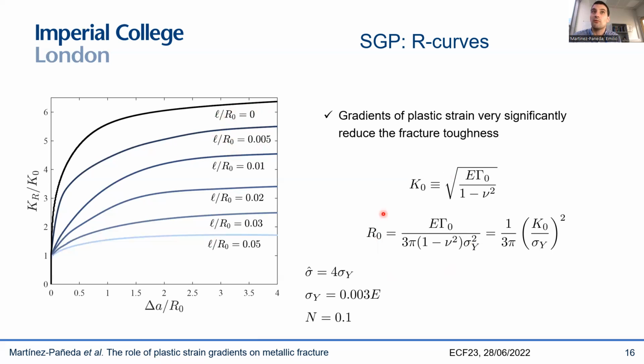But whenever you have a brittle fracture process, this fracture energy is going to be small, maybe on the order of a few joules per square meter, and therefore this value is going to be small and this value is going to be large. So this is suggesting that we're going in the right direction. It seems that our results should not be independent of this ratio. We know that depending on the fracture process, you can have a plastic zone that is larger or smaller, and that's going to make a difference on your gradient effects.